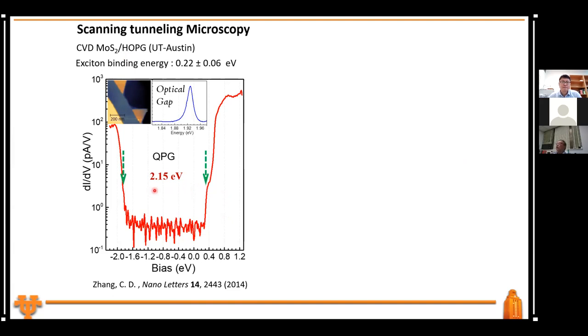But if we use this 2.15 eV, and then we also measure the optical gap, which is PL, on the same sample, not necessarily the same flake, but sort of the same genetic sample, then the exciton binding energy is large, but a lot smaller than what was originally theoretically predicted.